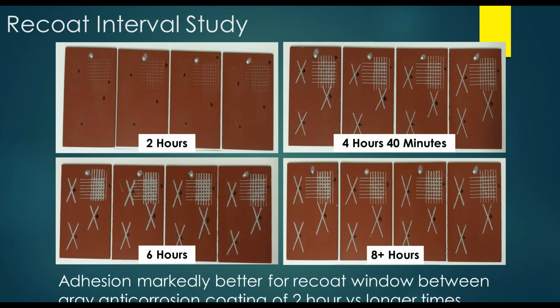A recoat study was undertaken, and in this we applied the gray anti-corrosion coating, allowed that to cure, and then at various time intervals we applied the red anti-fouling coating. What we found was that the adhesion was markedly better for recoat windows of 2 hours after the gray anti-corrosion coating versus longer times.